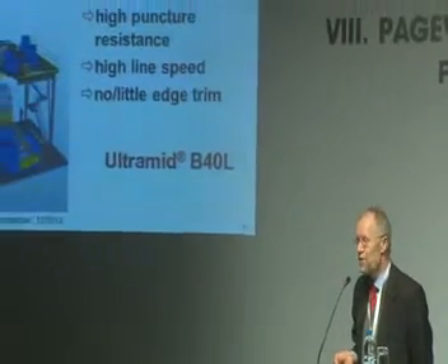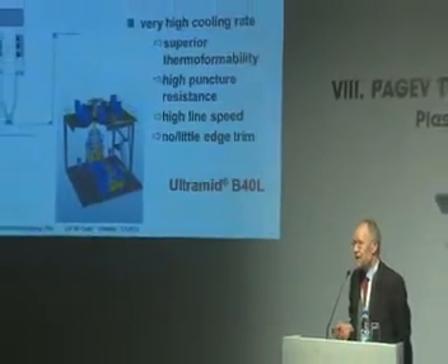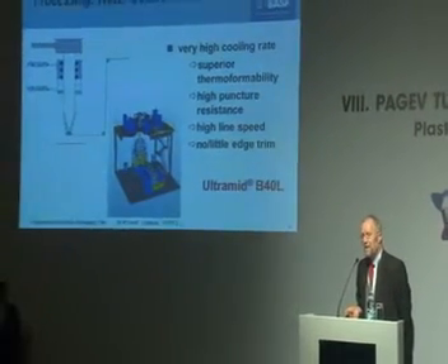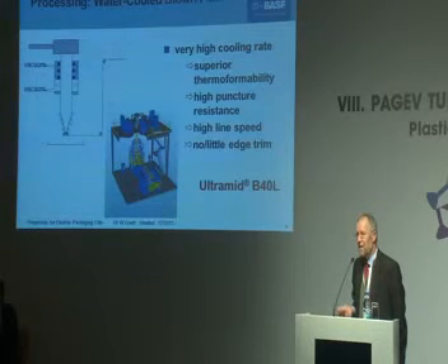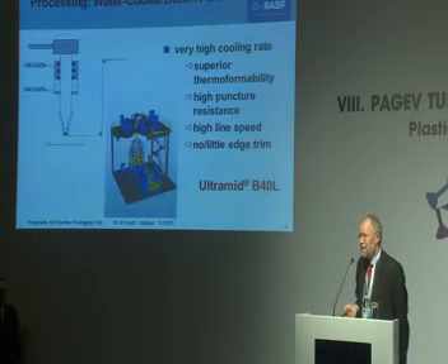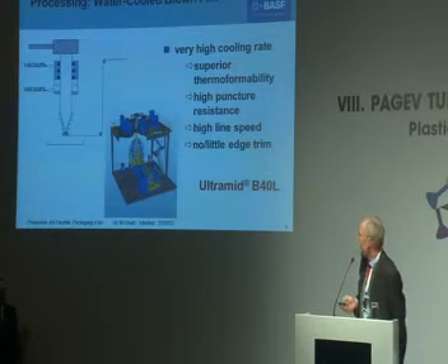A new technology that is coming up more and more is the water-quenched extrusion downward into a cold water tank. This is a technology that combines the very fast cooling of a cast line, due to the high cooling efficiency of water in direct contact with the hot melt, with the advantages of a blown film, of being relatively flexible, having no edges, no edge trim, no waste from that. So it's a new technology to make a cast film-like material with a blown film line, with very good transparency, very good thermoformability, particularly in the area of rather high film thickness.